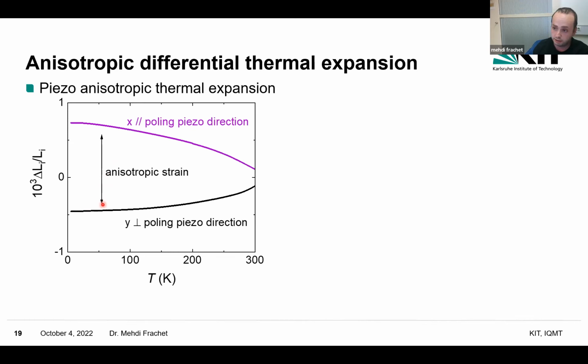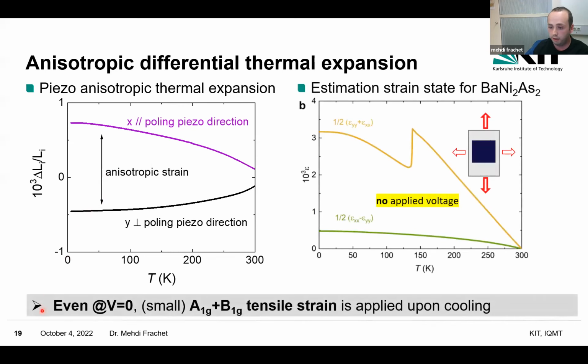So what that means for us is that even if you don't apply any voltage to the piezo, you just glue a sample on top of the piezo and you cool it down, you apply a bit of strain, and in particular a bit of anisotropic strain, even without applying any voltage. On the right side, you have a figure with an estimation of the strain state for BaNi2As2. You have this anisotropic part, B1g, which is only due to the piezo, and you have this A1g part, which also depends on the thermal expansion of the sample, of course.